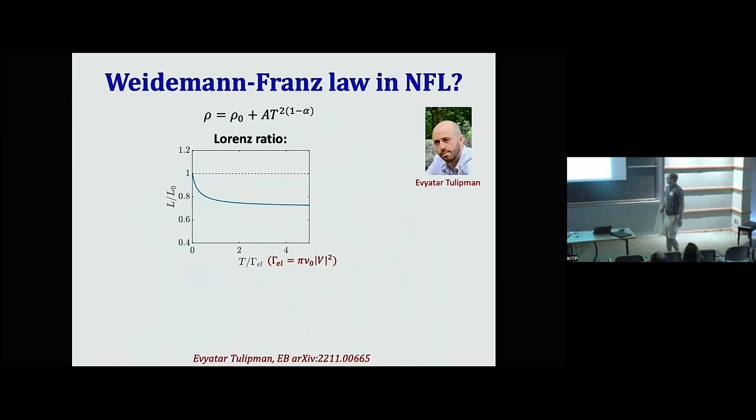We've computed the Lorenz ratio, this is Evyatar, who's here, as a function of temperature in this model. As T goes to 0, the Wiedemann-Franz law is actually obeyed, and it's obeyed for any alpha between 0 and 1. Even deep in the non-Fermi liquid regime, alpha bigger than half, the Wiedemann-Franz law is obeyed as T goes to zero.